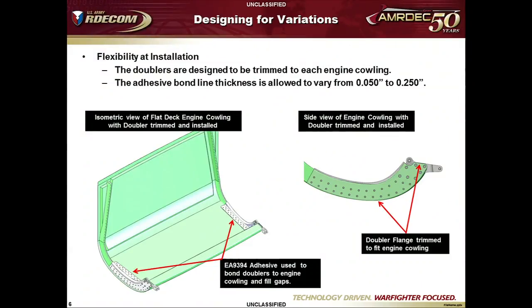We then put a couple of plies of fiberglass on top of that to protect the carbon fiber. So we now have an indication. If you see fiberglass being broken through, no problem, just do a normal fiberglass repair over it. As long as you're not damaging the carbon, it's fine. This is a CAD drawing of how it's installed. There are two types of decks out there. On the engine cowlings, there's a recessed deck and a flat deck. We've designed doublers for both of them.